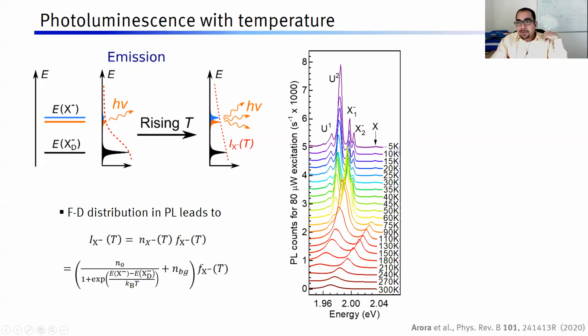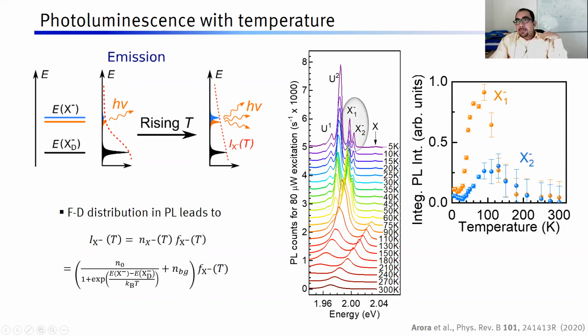So the top plot is at 5 Kelvin, and then we are increasing the temperature here. Let's only look at the trions part. You see that as the temperature is increased, the trions are rising in intensity. So this is what happens actually. There are two types of trions. One is blue, one is orange here. So first the intensity falls slightly and then it rises. Similarly for orange also, it rises and then it falls.